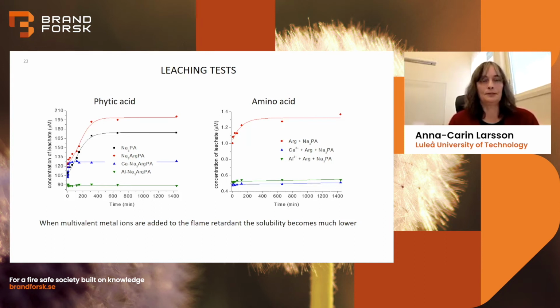And the blue and green at the bottom are the more insoluble versions with calcium and aluminium. So we can see that much less of the flame retardant is dissolved when we have calcium and aluminium ions in the system. Both the phytic acid and amino acid part stays on the cotton to a higher extent.